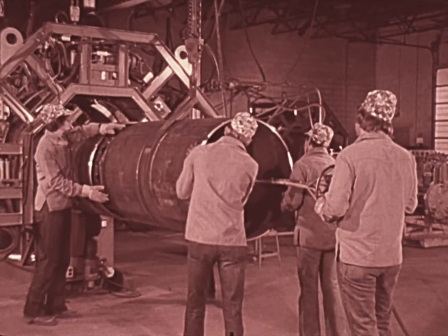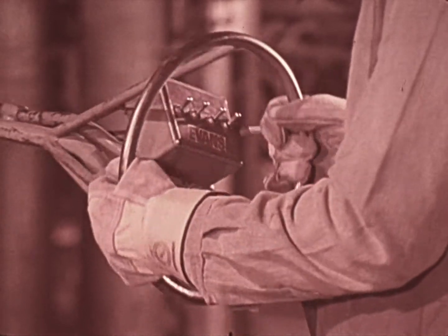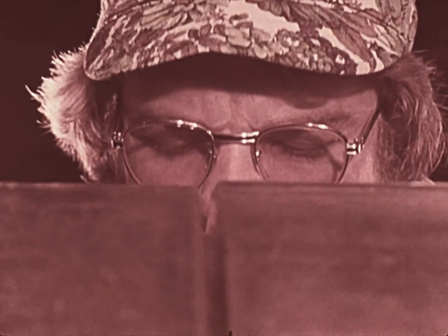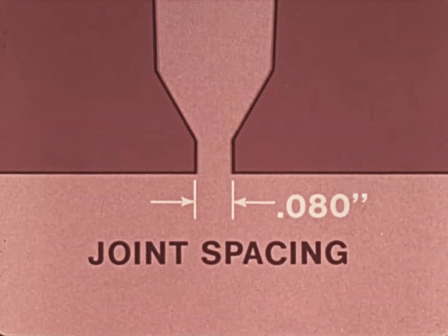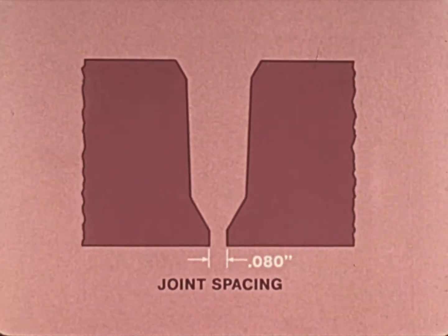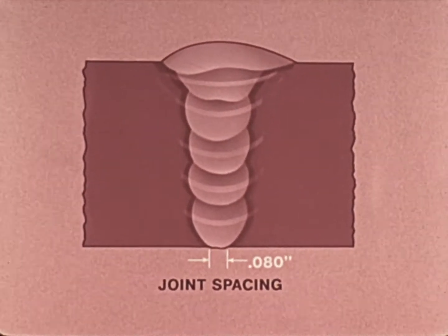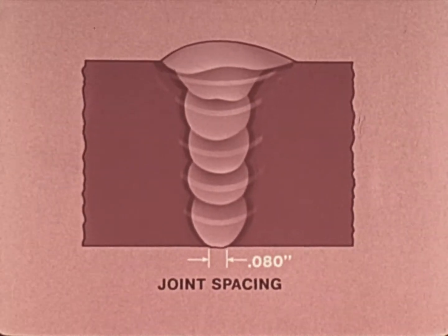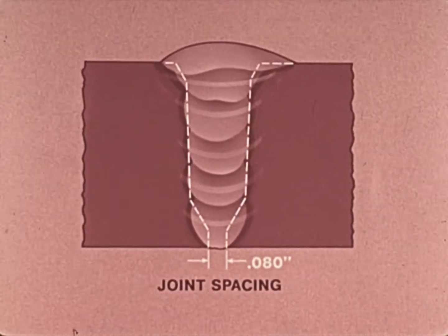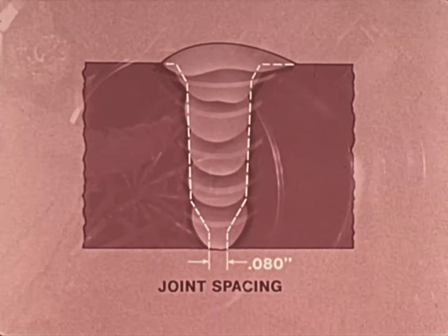In a single operation, the pipe ends are brought together around the clamp, aligned, butted, clamped tightly, all within seconds. Then the exclusive spacing feature of the lineup clamp separates the joint automatically to 80 thousandths of an inch. Hydraulic cylinders separate and maintain this predetermined distance with a force of 60,000 pounds. Specific joint spacing is required in automatic welding, since certain functions, including weld metal deposition, have been pre-programmed and preset. Automatic spacing aids in repeatability and uniformity of welds all along the line.